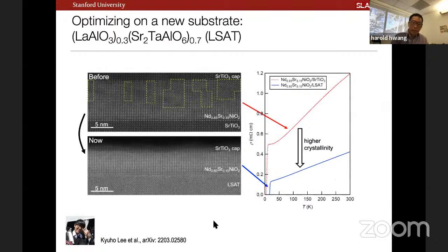Okay. So what does that buy you? Well, hopefully it buys you a little bit more fidelity in the resistivity and other transport studies that you might want to do. And just taking this comparison directly, you can see here the resistivity of this sample on strontium titanate. So it's quite a bit higher. You do see a superconducting transition, but by moving to LSAT, we have much higher crystallinity. And I'm going to spend some time talking about work that we've recently posted.